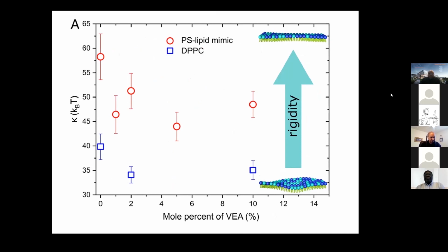This one shows you the bending modulus, kappa, as a function of how much vitamin E acetate is added. In particular, I just want you to look at the red circles here. They show that there is a precipitous drop-off in the bending modulus when you add even a little bit of the vitamin E acetate. What they extract from this is that the membrane rigidity decreases when you add the vitamin E acetate. It increases the membrane fluidity, and this suggests that the lung surfactant could squeeze out the lipids in it prematurely during exhalation, whenever you breathe out. And so that could lead to instability.